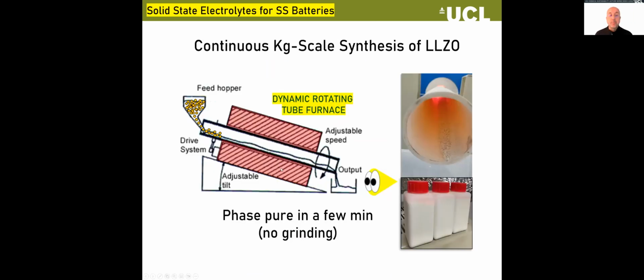Now, so what we then did was move to this continuous tube furnace, and this is where we put our powder in this time with the lithium precursor as well, and it's rotating. As you can see, oh, I was hoping the video would work. Okay, it worked earlier. So what we can see is that, first of all, the powder is now in direct contact with a hot tube. So this means you actually have to adjust the temperature slightly by a factor of about 50 degrees C. But once you do that, it works exactly the same.